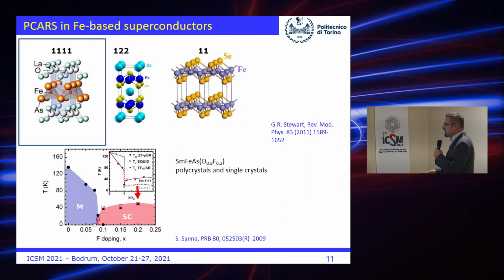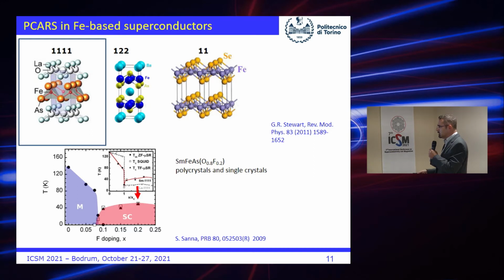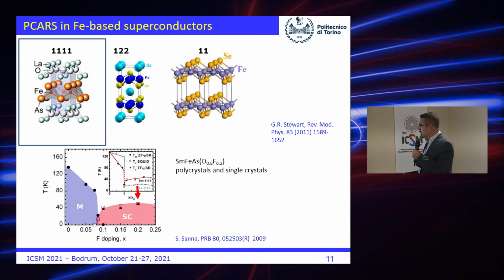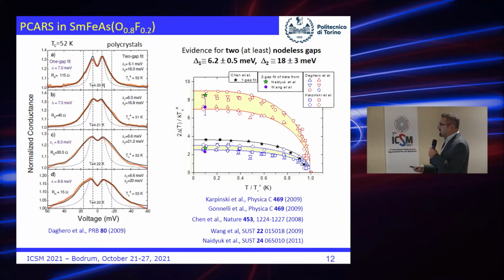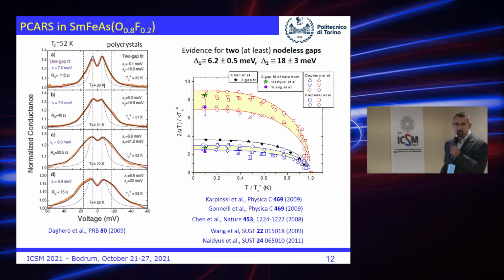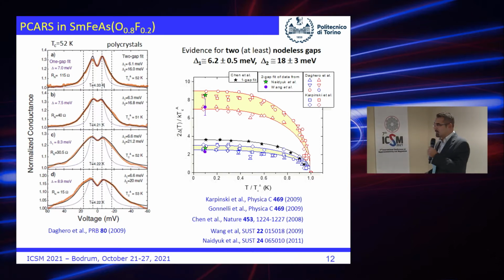Now let's start with samarium 1111. These are very old measurements in polycrystals and also single crystals. The doping is 0.2, so we are on the top of the dome. These are some spectra. When this paper appeared, we were in the middle of a single gap to multiple gap debate, and we showed that if you use a single gap fit, you can fit these features here, but you leave out most of the curve. So a two gap fit is possible, and it provides reasonably good agreement with the curves.